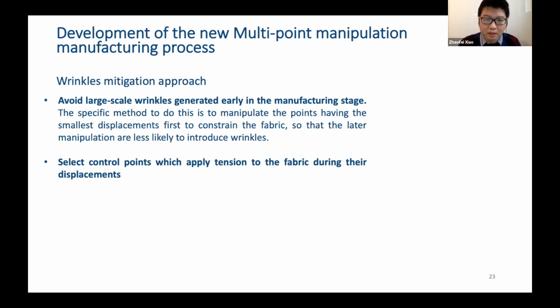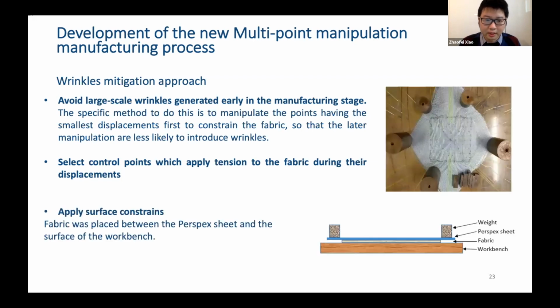So to do that, we need to manipulate the points which have the smallest displacements first to constrain the fabric, so that the later manipulations are less likely to reintroduce the wrinkles. And the second method is to select the control points which apply tension rather than compression to the fabric during their displacement. And the third method is we can apply some surface constraint.